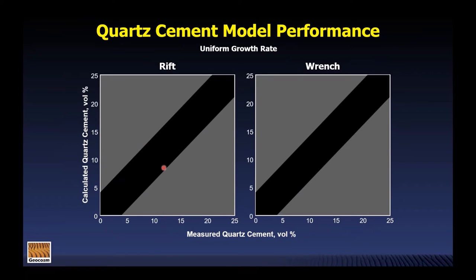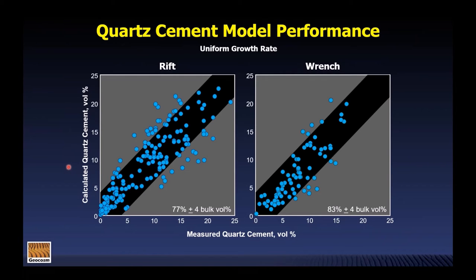And this black envelope here represents essentially the measurement uncertainty for quartz cement abundance. And so you can see here that in both of these large data sets, actually the model is doing a very good job at reproducing the observed quartz cement abundances in these sandstones. So my colleague Linda Bonnell, however, was not satisfied with this performance. Particularly for the rift data set, she wanted to see whether there was any systematic error in these models that could help us to improve them.